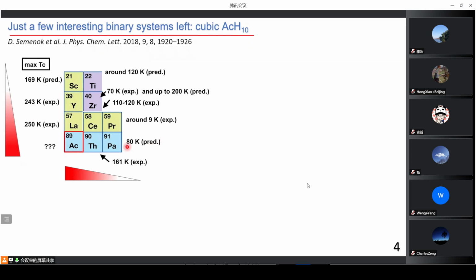Let's go now from the right side to the left side. For protactinium, protactinium H8 was predicted with TC 80 kelvins. The next compound is thorium H10. It was synthesized experimentally. Our group synthesized it, and 161 kelvins was found. And the next should be actinium, which should demonstrate higher TC than was found in thorium. The same story for lanthanum. For praseodymium hydride, almost nothing was found, no superconductivity, except maybe some small transition around 9 kelvins. Next compound is cerium hydride, 110, 120 kelvins. And the next is lanthanum, 250. So we expect that in the actinides the TC are systematically higher. For protactinium, it's higher than praseodymium. For thorium, it's higher than in cerium. We expect again that actinium H10 should demonstrate higher TC than lanthanum H10.